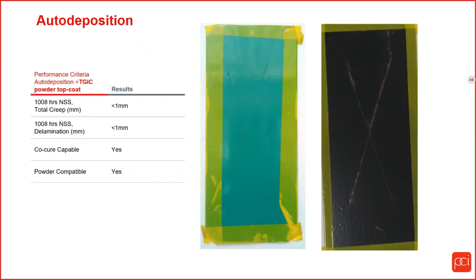So in summary, the acrylic did much better in most cases than the epoxy when coated with that one particular TGIC powder. We do have testing. This slide shows different testing that has been done with other TGIC powders, and the scribe creep is very minimal, less than 1 millimeter scribe creep back.